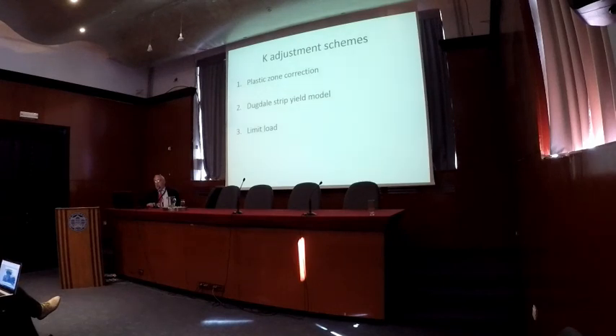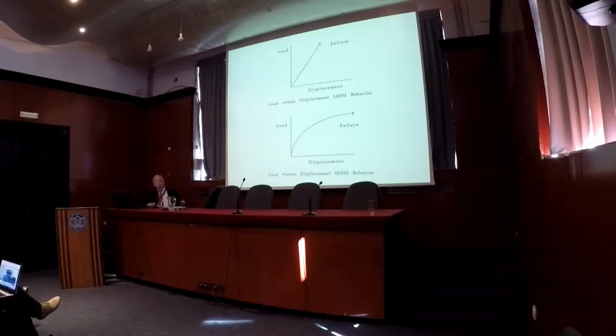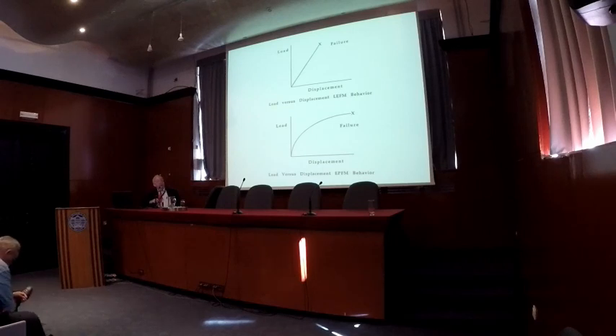But first of all, plastic zone correction. Here are some of the ways you could do it. The one by Irwin, then the Dugdale strip yield and limit load. Here is a way to tell that you have too much plasticity by looking at a load and displacement curve. You always do the load displacement curve in K1C testing. So if you have load and displacement, that's a straight line, that's a dead giveaway that you're in the linear elastic range, so you have no trouble. If you have nonlinear behavior like that, you could have a lot of crack growth or you could have a lot of plasticity. You can't always tell.